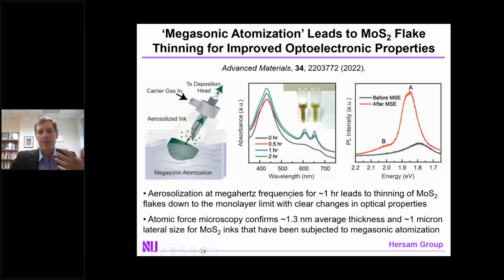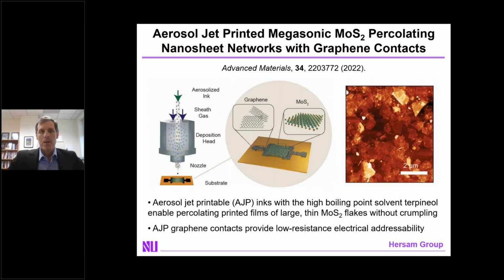And what we observed after doing this for timescales on the order of an hour are clear changes in the optical properties of our inks, which manifests itself not only in the absorption spectrum, but also the photoluminescence spectrum, thereby confirming that we've thinned down to the monolayer limit. We now take that megasonicated molybdenum disulfide monolayer ink, we print it onto substrates.